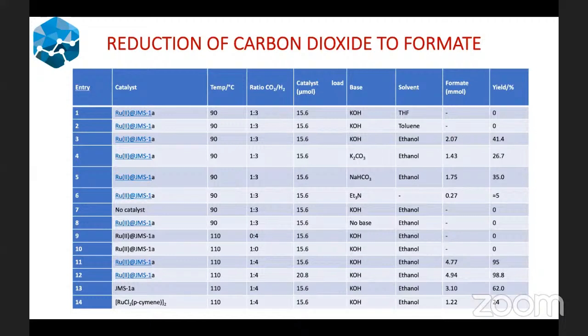And as you can see, potassium hydroxide is the one that is giving a high yield of 41.4%, followed by sodium hydrogen carbonate, that of 35%. It is very interesting to note that the triethylamine, which is normally used in a hydrogenation reaction, gave a very, very low yield of approximately 5%. What could be the reason for this?